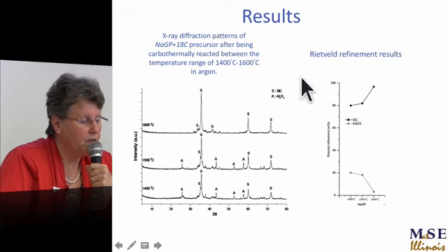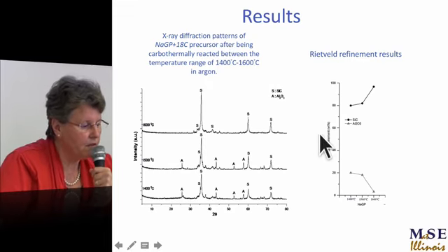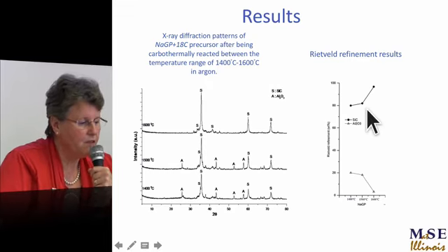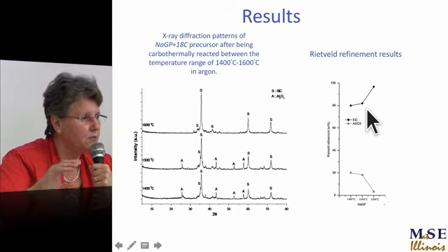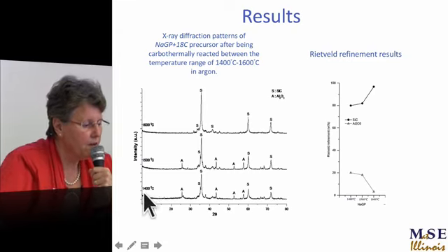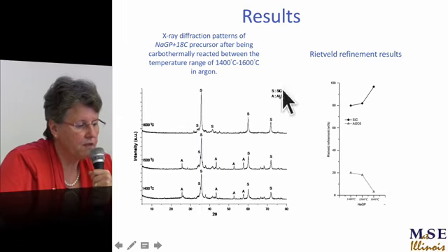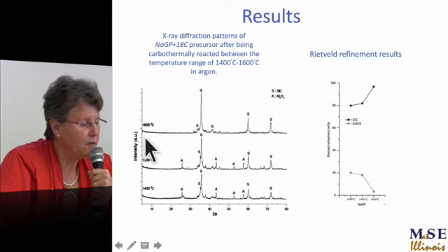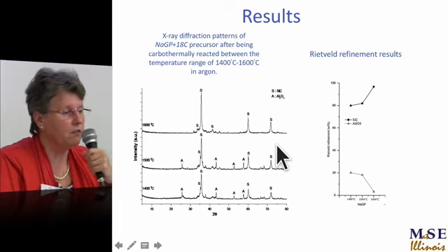His whole thing is, do X-rays and Rietveld, and Rietveld tells you how much of each phase you got. 80% of this, 20% of that. So at 1400 C you get alumina and silicon carbide. At 1500 C more silicon carbide, just a little alumina. At 1600 C silicon carbide, about 97%.